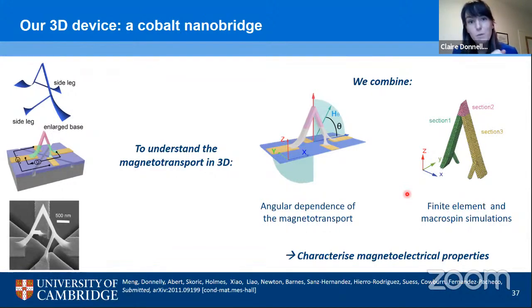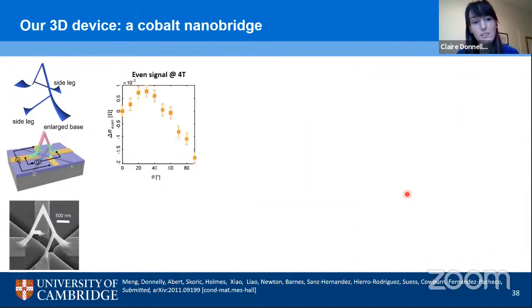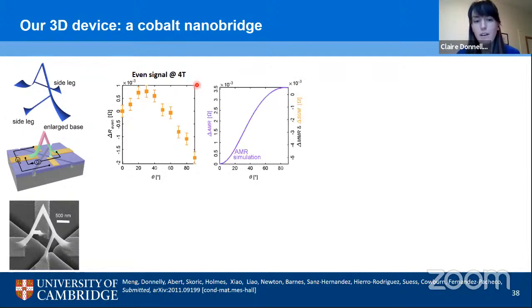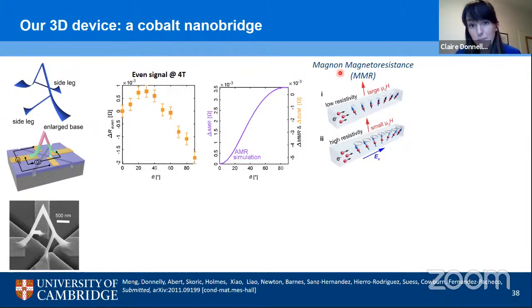And I'm not going to go into too much detail, but one specific point that I want to focus on is quite an unexpected finding that we discovered. And that was when we looked at the even signal of our magnetoresistance, and this is applied at 4 tesla. So when we look at the even signal as a function of angle, we see quite an unusual angular dependence with a peak in the resistance at about 30 degrees. Now, the even signal is the part of the signal that corresponds mainly to the AMR, so the anisotropic magnetoresistance. However, when we simulated the AMR, we saw a very different angular dependence. And what we realized is that in order to understand and actually reproduce our structures, we needed to take account of the magnon magnetoresistance.